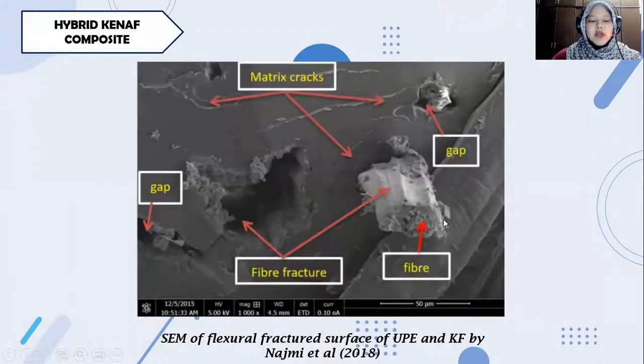Next, on hybrid kenaf composite, you can see they have a few gaps, few fiber fractures, and few matrix cracks. This picture is from SEM of the flexural fracture surface of unsaturated polyester and kenaf fiber by Najmi et al. in 2018. This is because the link between the matrix and the fiber reinforcement is weakened relative to greater fiber loads. Hence, the smaller the fiber load, the stronger the connection.